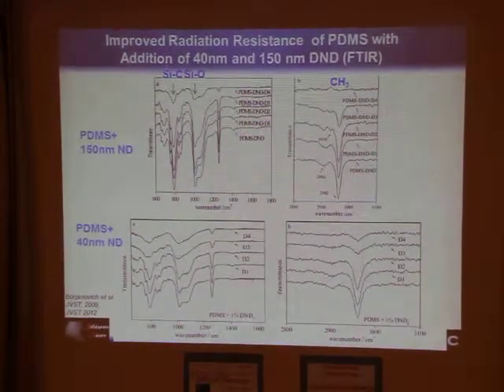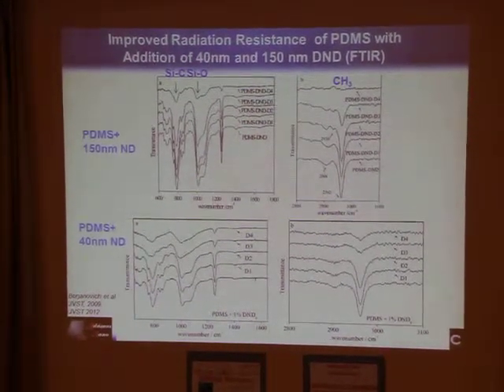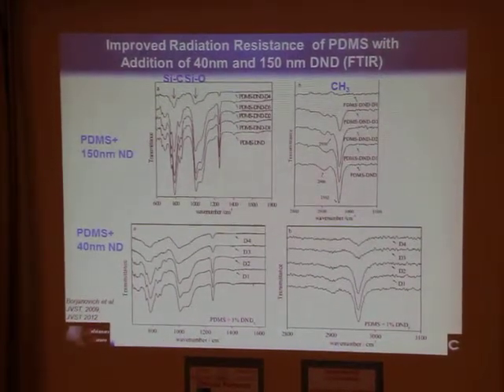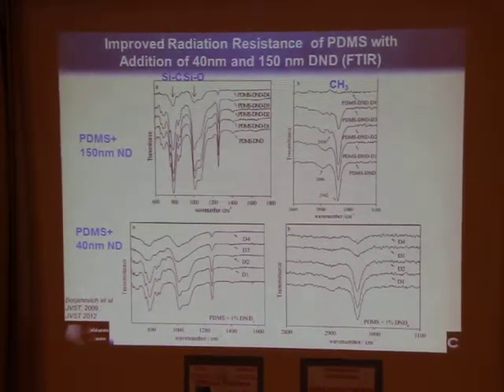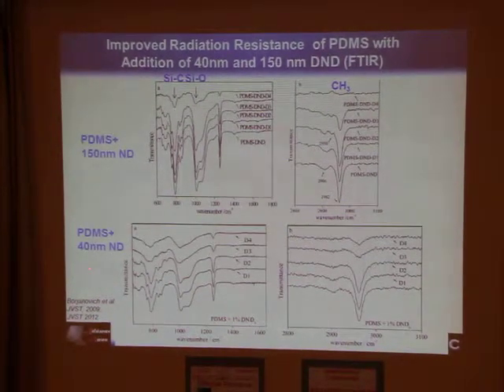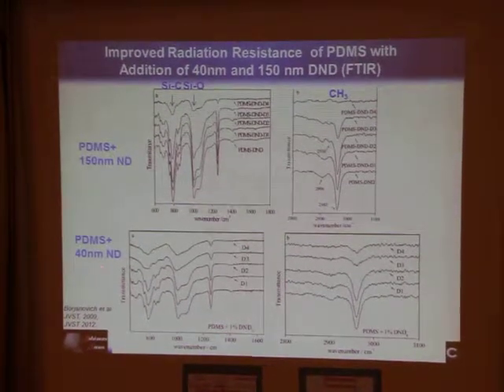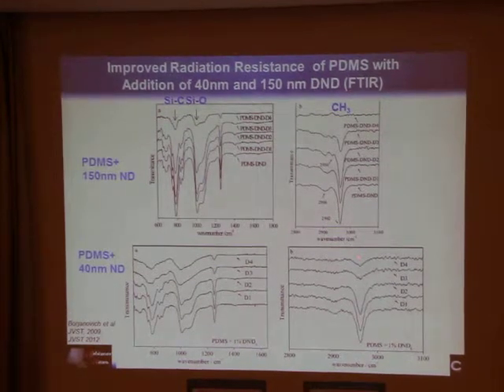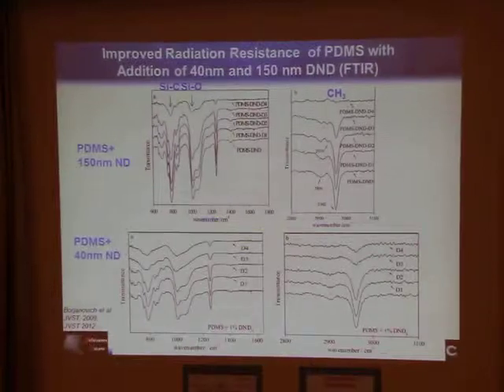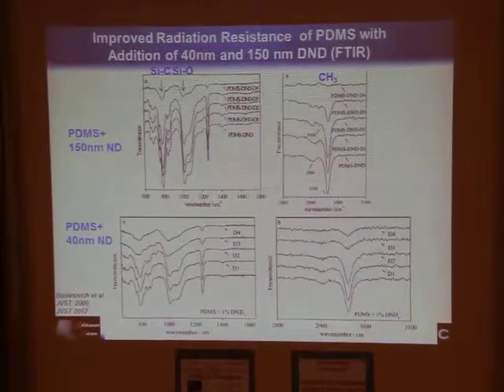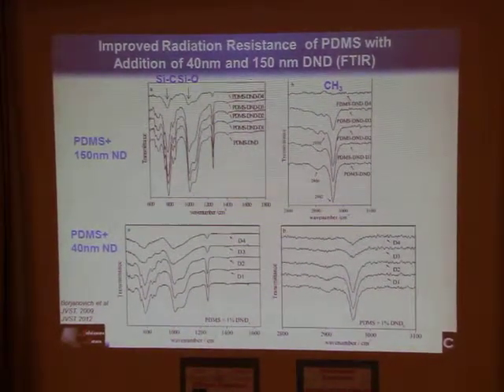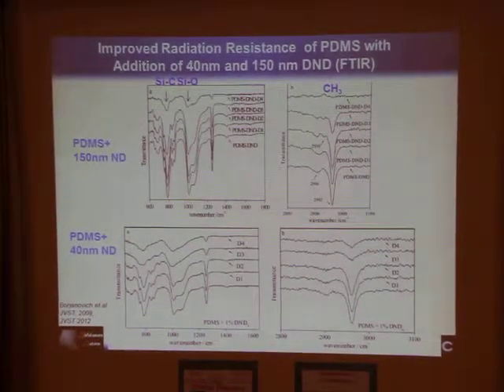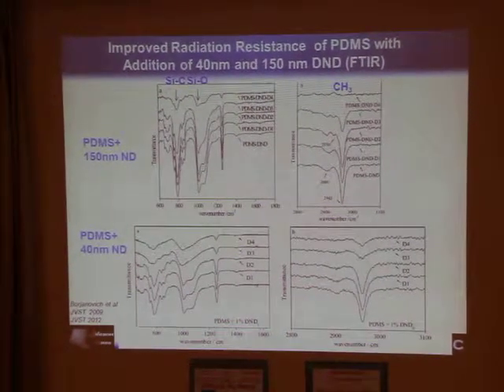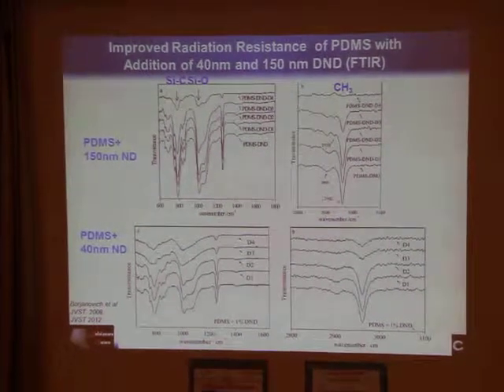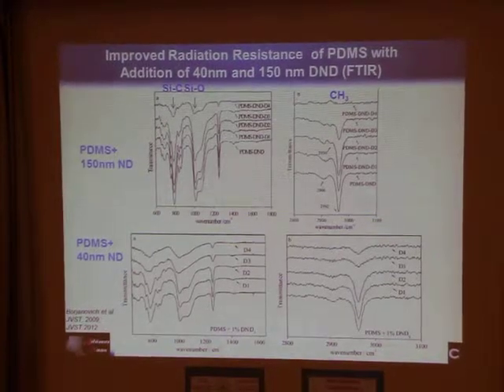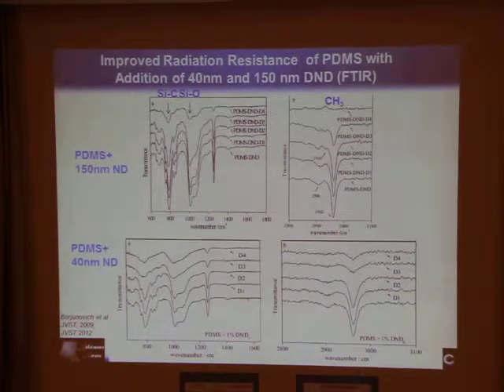So what happens if we use smaller size nanodiamond particles? The upper spectra show the same results that we saw on the previous slide, and the lower pictures show results for PDMS plus 40 nanometer nanodiamond particles. What you can see is that in this case the CH3 characteristic peak is also preserved. So we conclude that for smaller nanodiamond particles, radiation resistance is better than for larger aggregates of nanodiamond used in PDMS composites. So in general, there is a 20 times improvement in radiation resistance, 20 times being the difference between the doses when characteristic features disappear for pure PDMS as compared to when these features disappear for the nanocomposite.